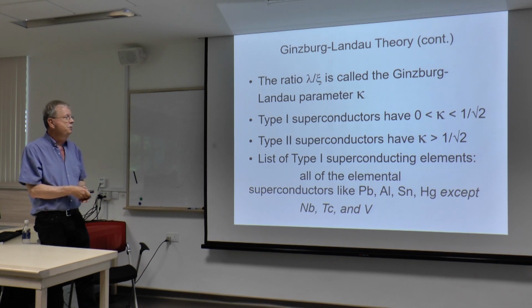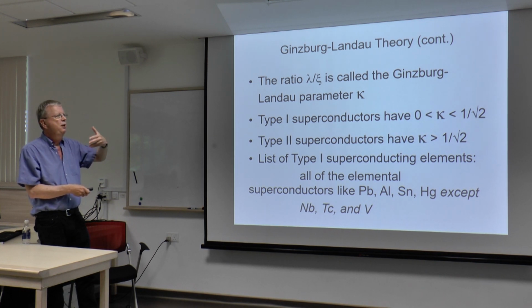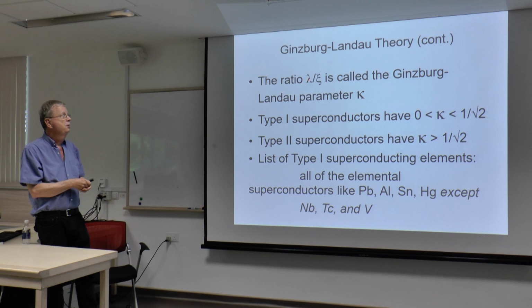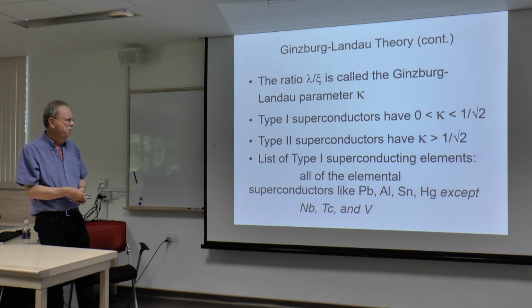And if it's a type 2 superconductor, which is talking about the energetics of letting the flux lines penetrate and lowering the energy while keeping part of the sample superconducting, then you have a penetration depth that's larger than the coherence length. So all of the elements are type 1 except those 3. We talked about technetium, which is a non-naturally occurring element that comes out of nuclear reactors, Technetium 99, at least when I worked at Los Alamos. Al Georgi got that from Oak Ridge, and vanadium. And we talked about how the ratio between Hc2 and Hc1 for niobium wasn't all that large. It was maybe a factor of 2. And of course, for some of the A15s, it's huge numbers.